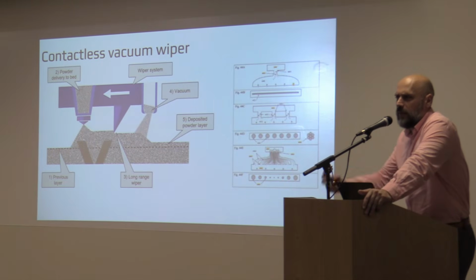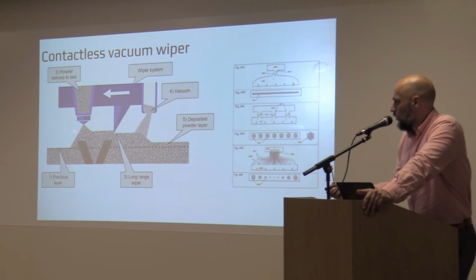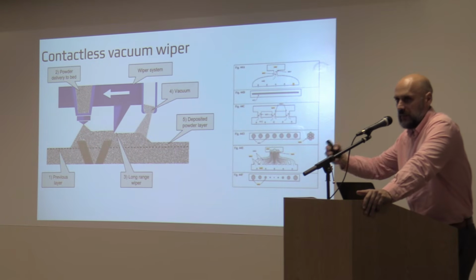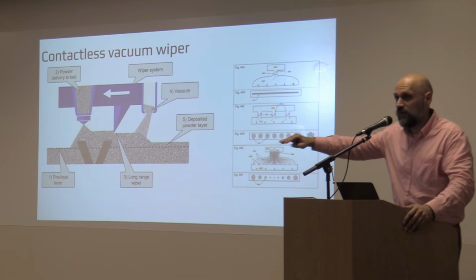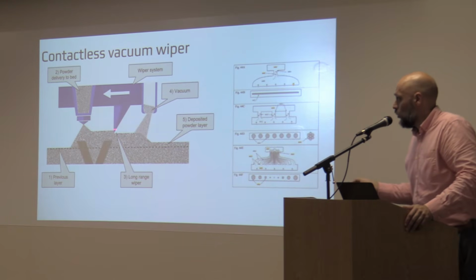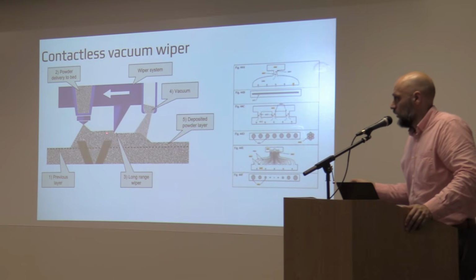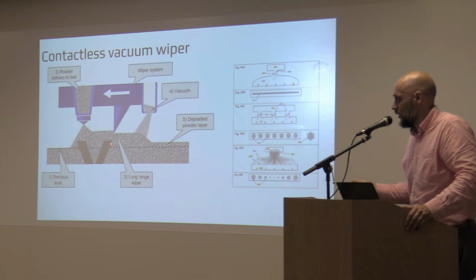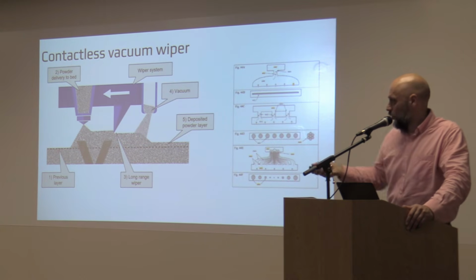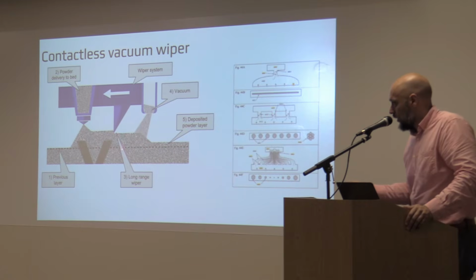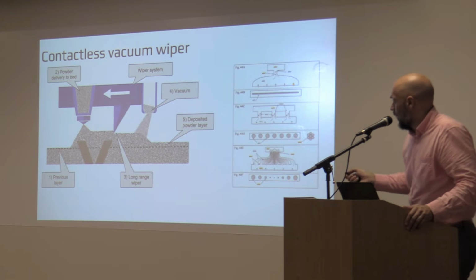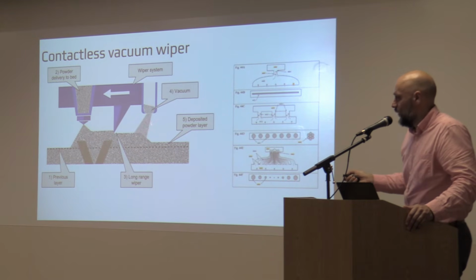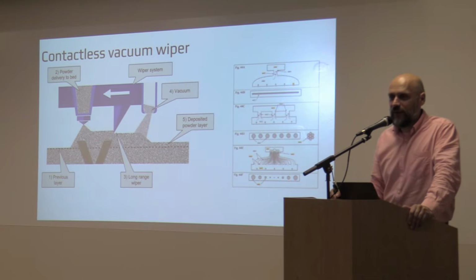I said the layer height is maybe 50 micrometers. We're going to put 300 now. So this is like 300 micrometers. Second step, because you're dropping it, it's kind of free falling. It is not flat, right? So we put a wiper here. We call it the longer range wiper because this is still like 200 micrometers now. But it's flat and consistent because you hit it with a hard wiper. Our parts are deep down here, right? And then at the end you have a vacuum that sucks the excess powder off.